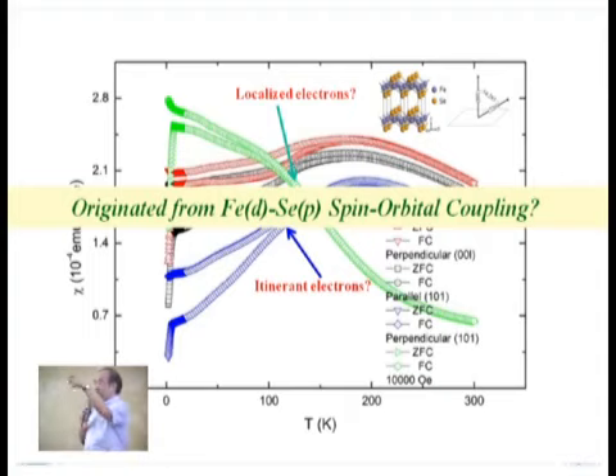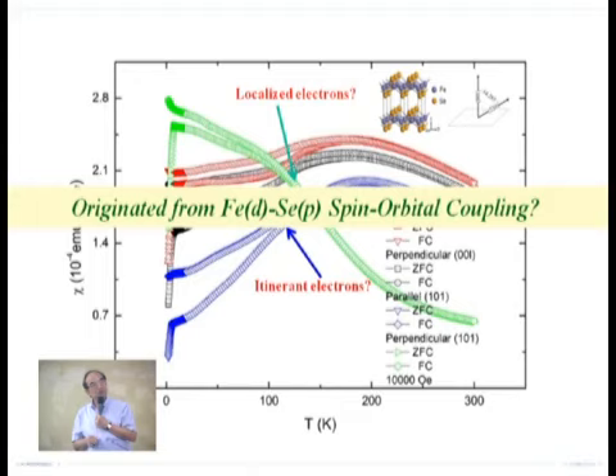Which means this iron and selenium, you have a d orbital, like copper oxide, and oxygen you have a p orbital. And here you have d and p orbitals, and that kind of orbital effect becomes essential. And it indicates maybe there are two kinds of electrons, with spin orbital coupling. You have some itinerant, some more localized, and that's how your spin fluctuates. And it also gives rise to this 100 Kelvin distortion. So based on the data, we speculate that, and from the fluctuation get to superconductivity.